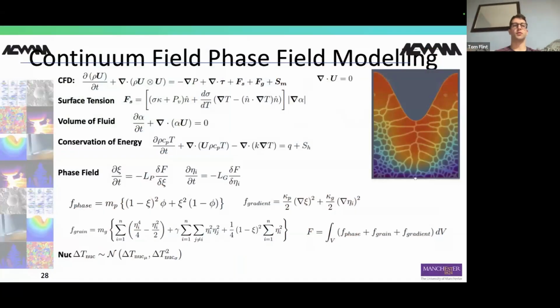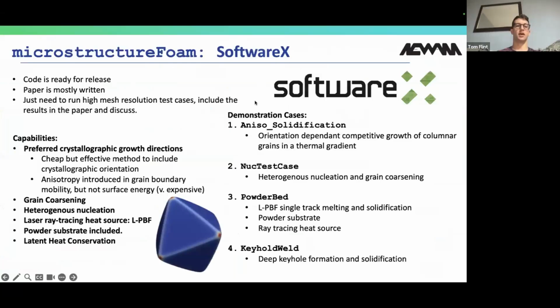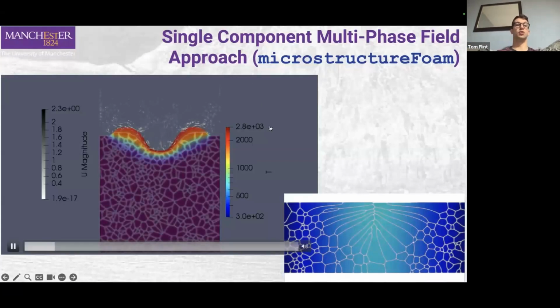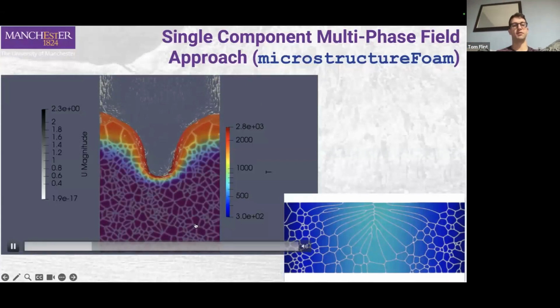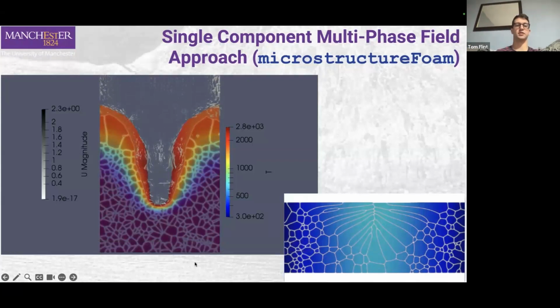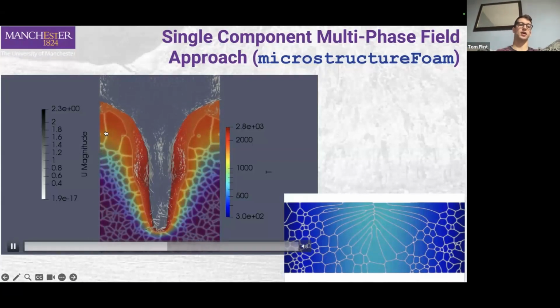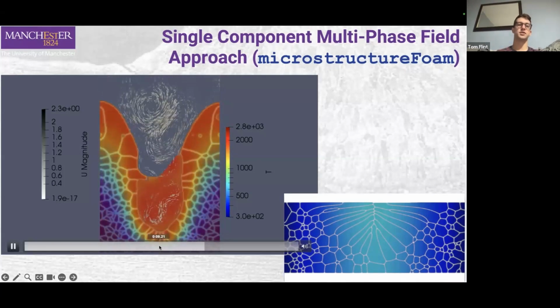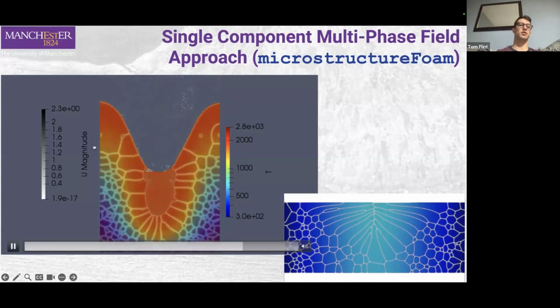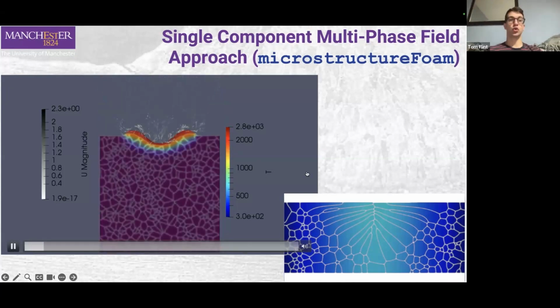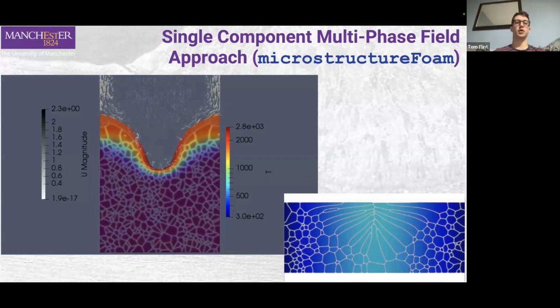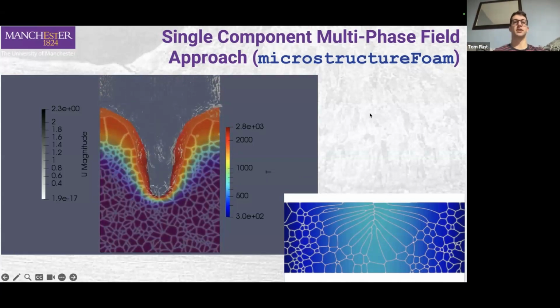And then also we've done work, and again, this is a simplification. So we're probably going to release this code, although if we release the higher fidelity one, maybe we'll not even bother releasing this. But this is another work in progress that we're hopefully going to release soon for the community. This tool has the ray tracing plus the evolution of the microstructure. So again, solving a slightly different set of phase field equations, slightly simpler, but having all the thermal fluid dynamics in there and the solidification. So a very powerful tool, quite computationally expensive, but you get a lot for that computational expense.